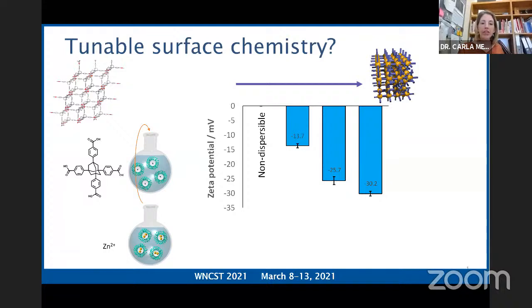If we carry out the synthesis under conditions of excess ligand, so our microemulsion with metal is added to our microemulsion with ligand, and we control the rate of addition such that the crystals grow under conditions of excess ligand in all cases, we can see that we can start to tune the crystal structures so that under conditions of the highest excess ligand, we get the most negative zeta potential. So these were in fact dispersible.